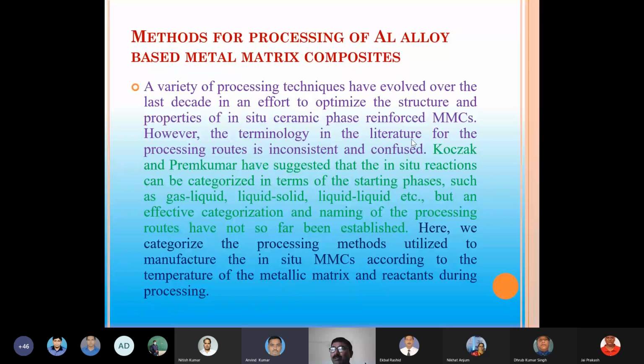So if you have an aluminium matrix, and in that you have added either titanium carbide, aluminium oxides, silicon carbides or boron carbide from the outside, then it is called an ex-situ metal matrix composite. But suppose I need to develop an aluminum, titanium, carbide metal matrix composite.